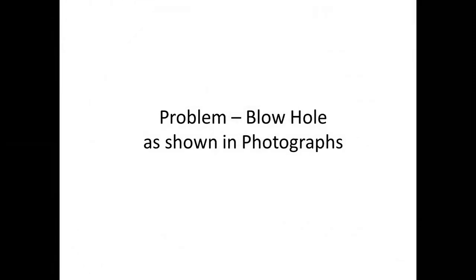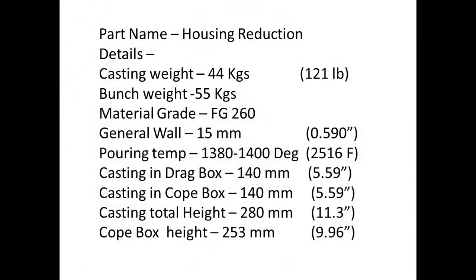Now we'll go for the case study. This part was facing a problem of blowhole rejection. That rejection was around 30 to 40%. Details are given. Casting weight 44 kgs, which means 121 lb. Bunch weight, material grade, general wall, pouring temperature, casting height in drag box, casting height in cope box, all these have been converted into inch, lb, and Fahrenheit. Then cope box height.